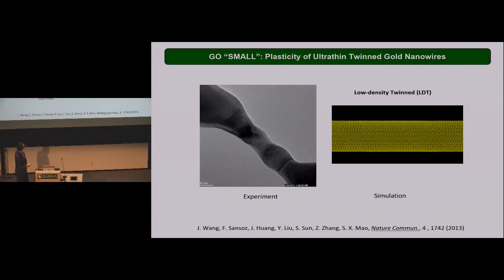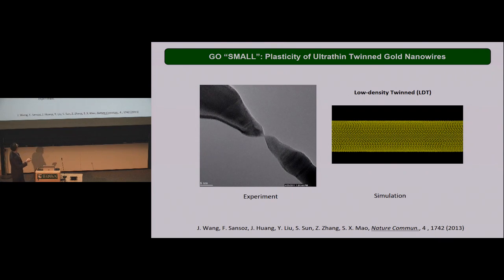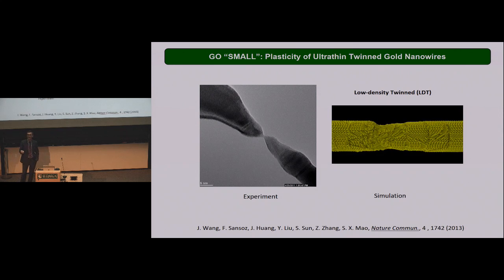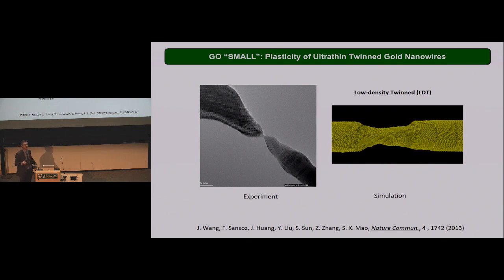And so you can extend this wire. The difference in contrast you see in the video represents the nucleation of dislocation from the free surface. At the same time, we perform atomistic simulation, and they actually describe exactly the same behavior. So it's one case where we have perfect agreement between the simulation and the experiment. And the reason for that is because the nanowires are so small, we can model exactly the same thing in simulation. We don't need a lot of resources to do this simulation.